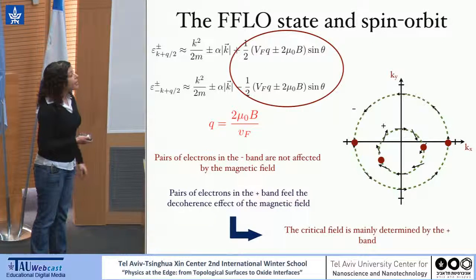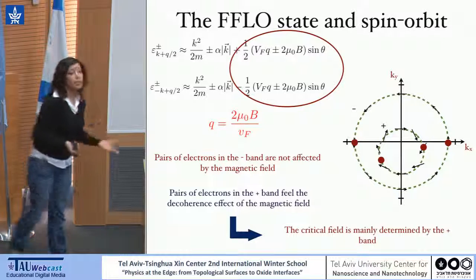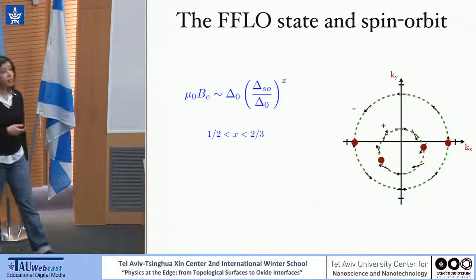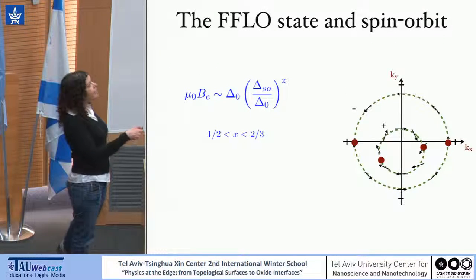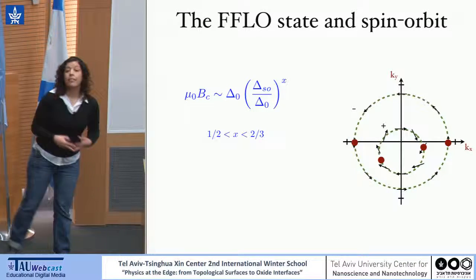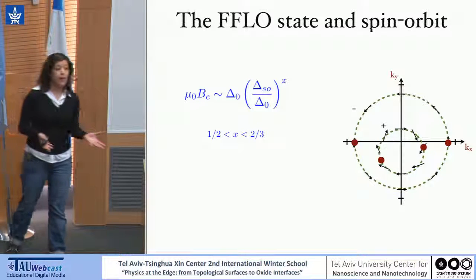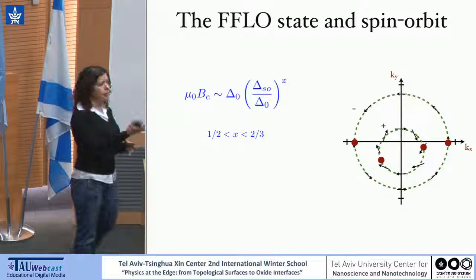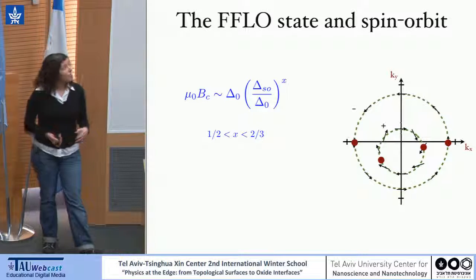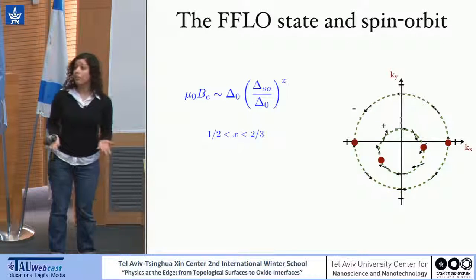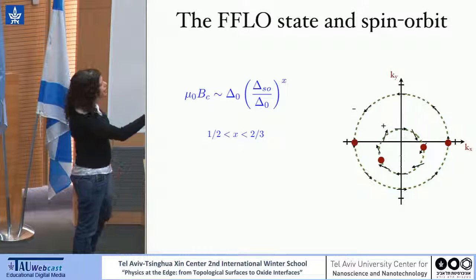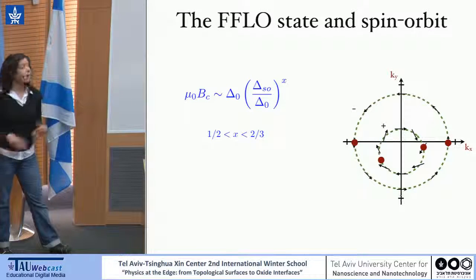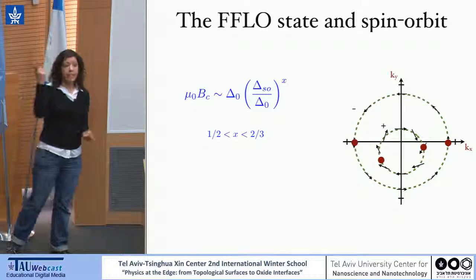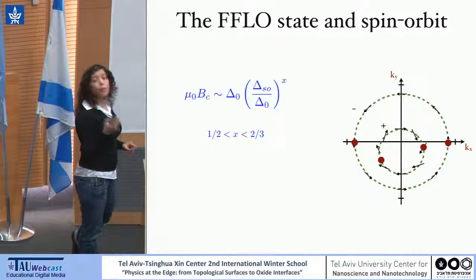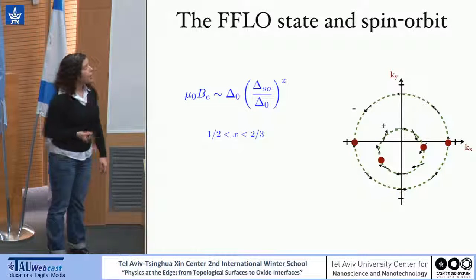And from that, we can ask what will be the critical field. The critical field of the system is going to be enhanced by a factor which depends on the ratio between spin-orbit coupling and the bare superconducting gap. For example, if we think about the LAO-STO, that's a factor of 2 orders of magnitude. There is a power there, which is a matter of details. So let's say 1/2. It can increase the critical field by an order of magnitude, for example, for the LAO-STO.